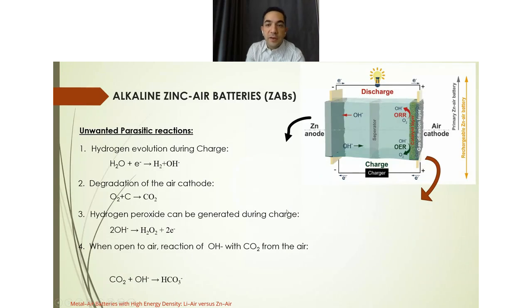This is due to some difficulties that zinc batteries face when they are applied as a rechargeable battery. For example, during charging, when you try to increase the voltage, you may accidentally generate hydrogen gas instead of zinc, because the reduction potential of hydrogen is very close to zinc, and zinc has a lower reduction potential than hydrogen. So sometimes you end up generating a lot of hydrogen gas instead of zinc, and you're losing performance through the HER, or hydrogen evolution reaction.